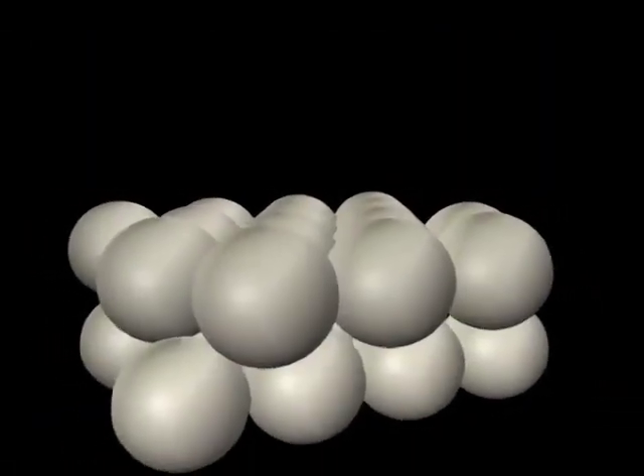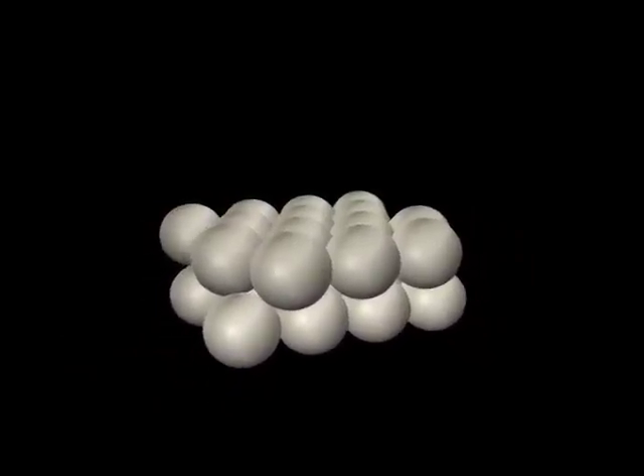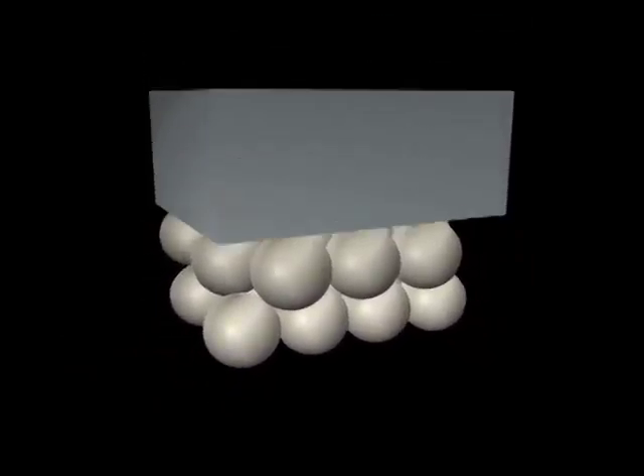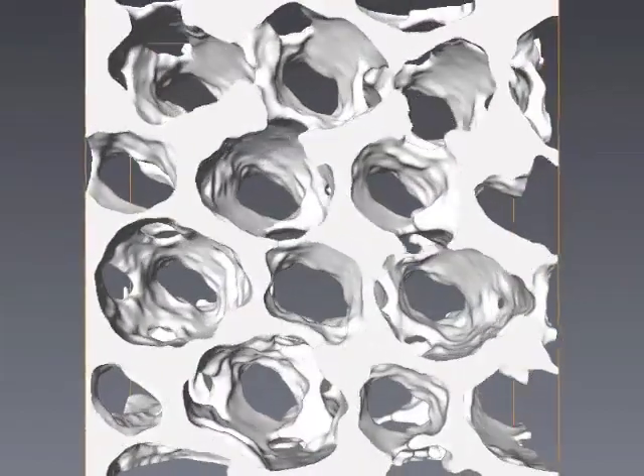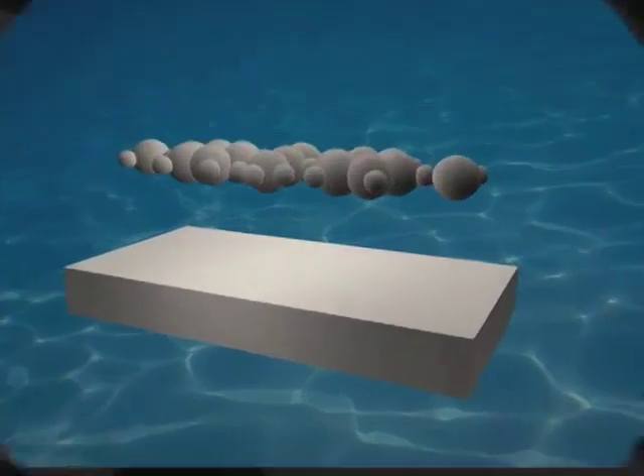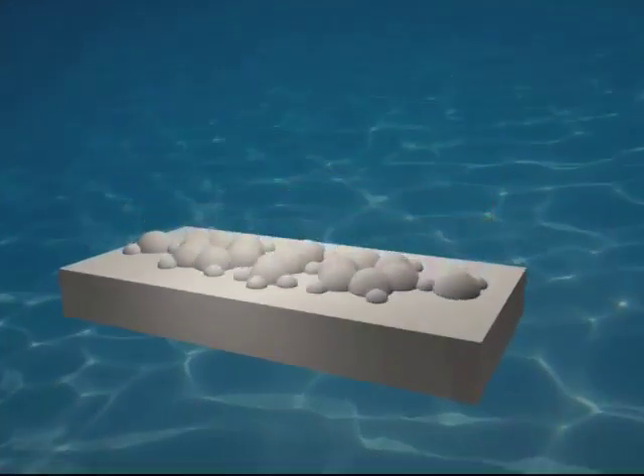ETRI developed an inverse opal photonic crystal which is prepared using a periodical assembly of microspheres in 3D as the template. The template is dipped or filled with an imprinted solution containing BPA, cross-linkers, and functional monomers. After gelation of this solution, the microspheres and BPA are removed by solvent washing to generate the photonic crystal structure with BPA imprinted material in the skeleton.